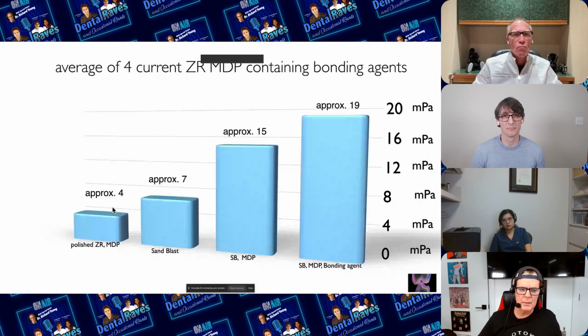And then we put MDP primer on there on 4 different companies. I don't want to beat any of the companies up right now, okay? And then I put cement on there, and we looked at the cement or composite with an MDP primer, but with no sandblasting. The average bond strength of the 4 materials was 4 megapascals.